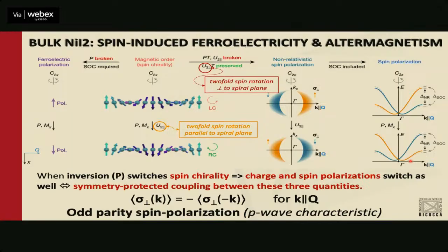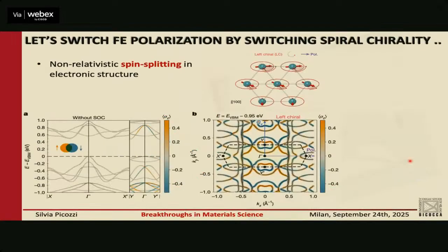So that was symmetry prediction, and we verified it with DFT. Again, it's a band structure with many directions, but let's just look at this one. This is the band structure along a certain gamma-y direction, parallel to the propagation vector of the helix,